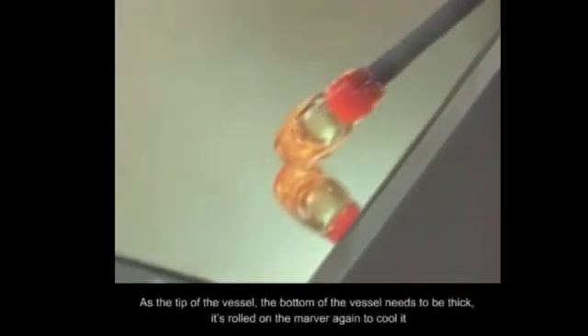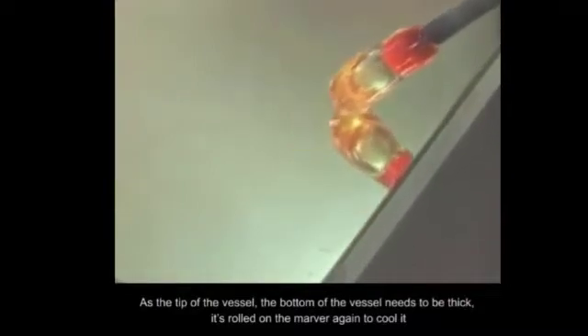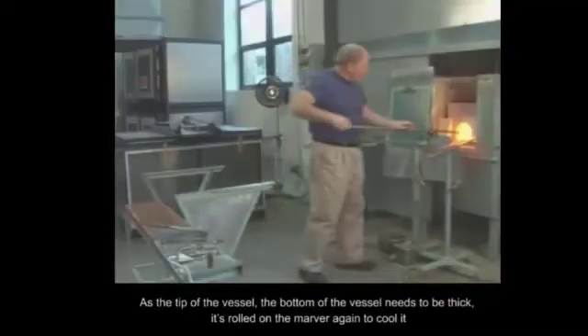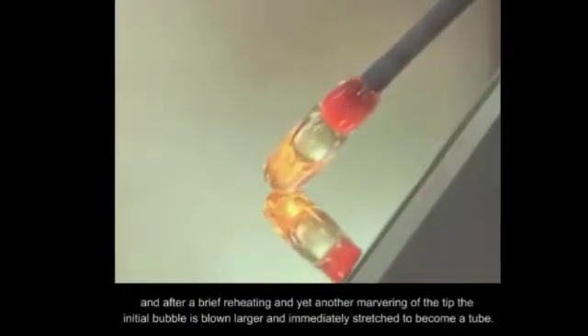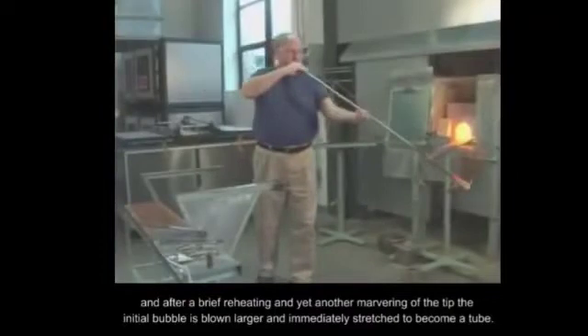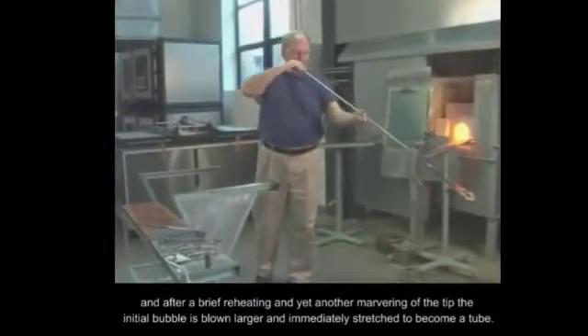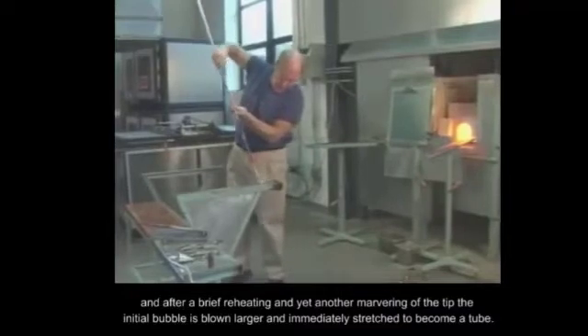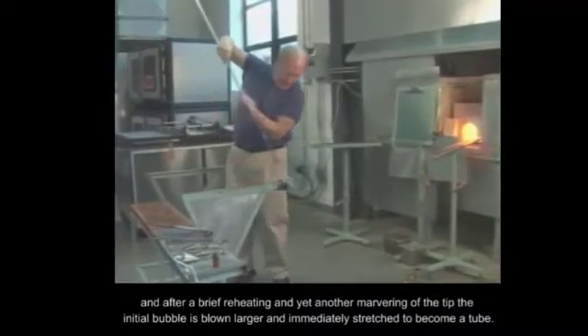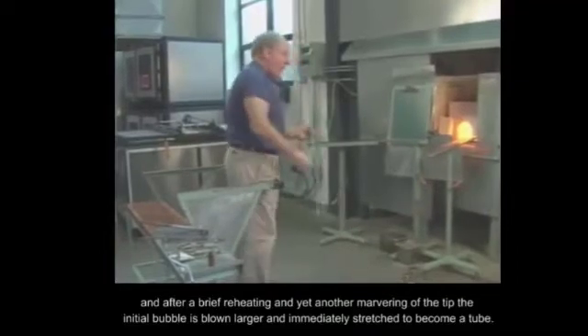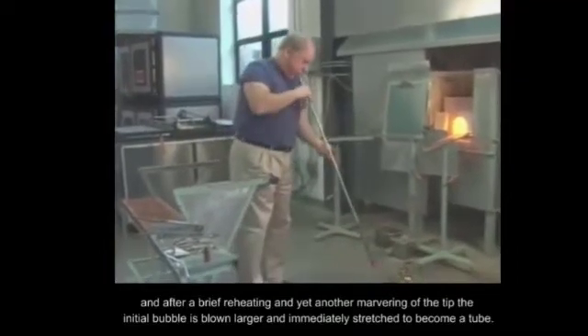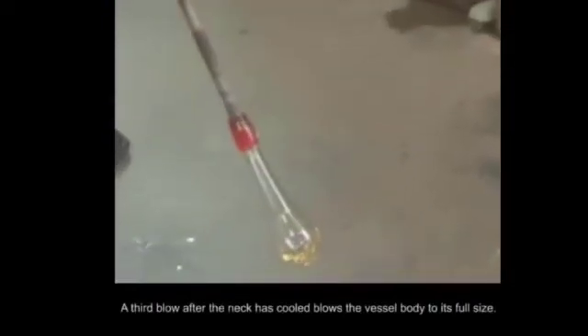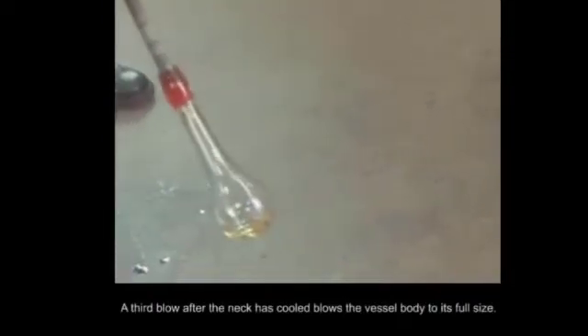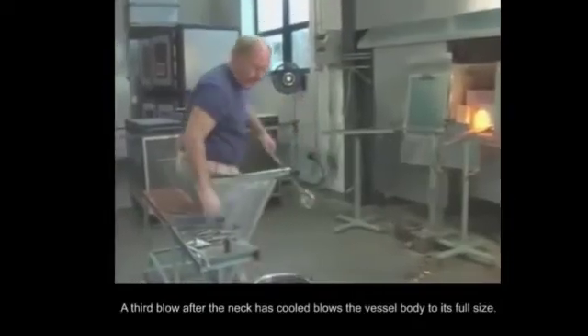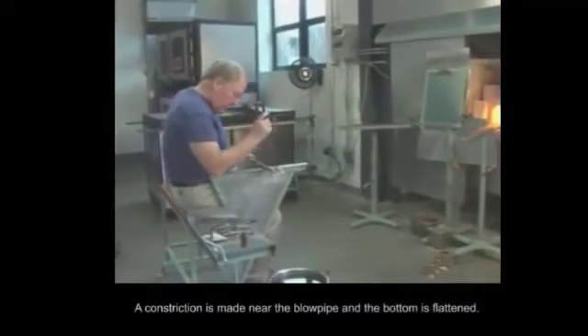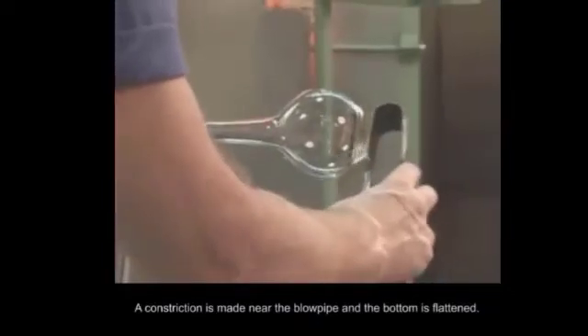The bottom of the vessel needs to be thick. It's rolled on the marver again to cool it, and after a brief reheating and yet another marvering of the tip, the initial bubble is blown larger and immediately stretched to become a tube. A third blow, after the neck has cooled, blows the vessel body to its full size. A constriction is made near the blowpipe, and the bottom is flattened.